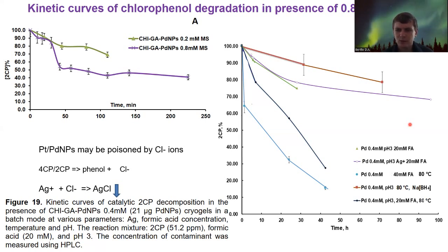Therefore, what we also did, we checked the catalytic activity of the catalyst in presence of sodium borohydride, and in this case also we didn't observe the complete conversion of chlorophenols, and probably the geometry of these particles is not suitable for significant adsorption of substrate to the surface, or the release of the product of a reaction is the limiting stage of this process.